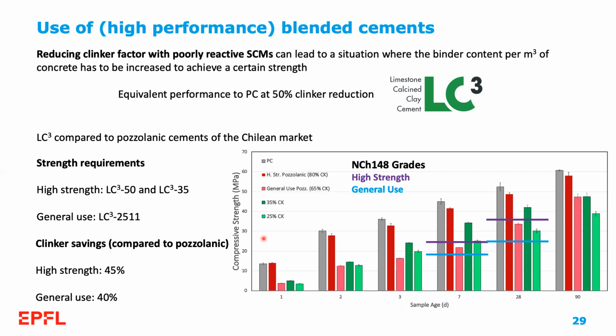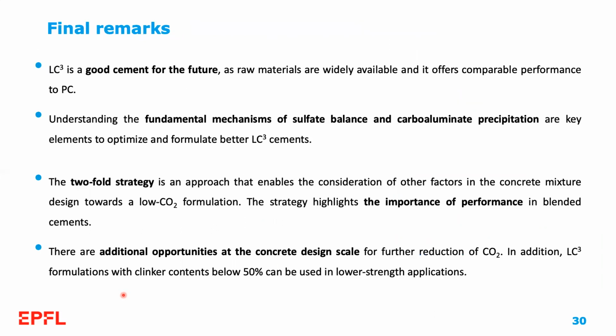This leads us to clinker savings compared to pozzolanic cements of 45% in the high strength grade and 40% in the general use one. So a huge opportunity to develop lower CO2 cement, even in markets where PC level strength is not required or is not used to be implemented in the standards.